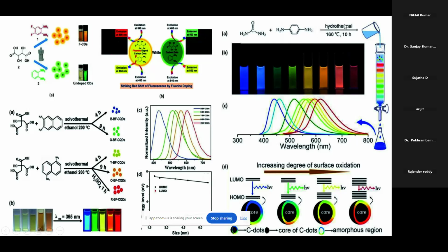Then the hydrothermal method discussed here is at 160 degrees. According to this also, we can get different types of luminescence property of the CQD. Then with increasing degree of surface oxidation, the HOMO-LUMO band gap shrinks. The band gap gets lower when it has the core structure. The core structure usually has sp2 structure, and the outer shell has sp3. According to this hybridization, the amorphous region will also be present there. When we image them, we couldn't obtain fringes because of the amorphous partition in it.